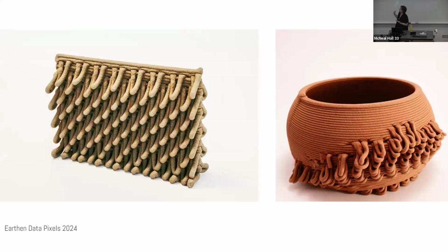So this is an image of that Ely clay in its unfired state, and you can see that it's a really beautiful gray-green. And then we fired it to a full cone 4, which is a real, usable clay. And it became this really deep reddish brown with an incredible luster, likely from the white sands that came from White Sand Beach. We have samples here, so again, take a look.